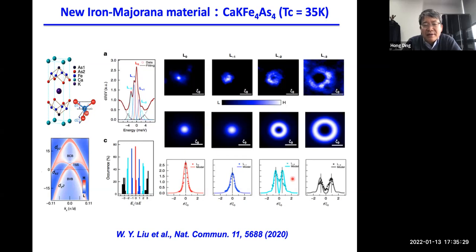We stumbled on this material, which has a high Tc. We looked at the band structure and realized this may become topological. Then we went on and did the ARPES and also the STM. Not surprisingly, we actually see the Dirac cone slightly above EF in ARPES, and we also see the zero mode. The nice thing about this is that we see the bound states, zero, minus one, minus two, minus three, follow the pattern as predicted by the simple theoretical simulation.